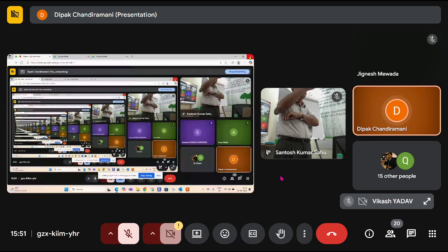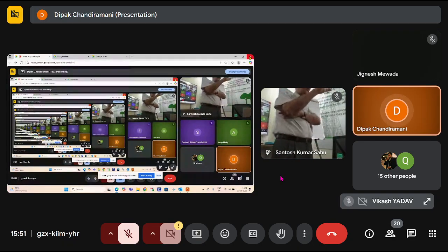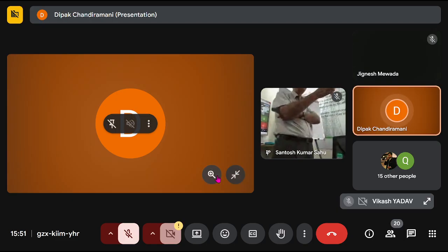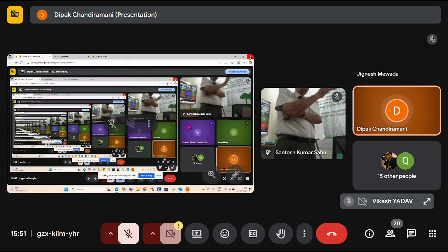And you're using that rebound tester or what? Yeah. So that is very sensitive to the surface finish, and also a slight angle change here and there makes a big difference in the value. That rebound testing is a very difficult thing to use. I found problems with the surface finish. A little bit of scratches more or less makes a totally different value. So those things I have no answer really. But the basic concept is base metal, HAZ, weld, HAZ, base metal, like that. That is the norm.